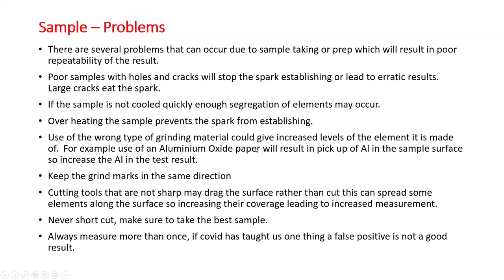Okay, so what are some of the problems? Several problems can happen during actually taking the sample or actually preparing the sample, and it will result in poor repeatability, and that gives you poor results. Poor samples with holes in, cracks in will stop the spark establishing or lead to erratic results. A large crack actually eats the spark. So if you've got cracks in your sample, the energy that's in a spark system is actually drawn into that, and it actually pulls the energy out of the spark. So in some cases, it actually stops the system being able to measure.